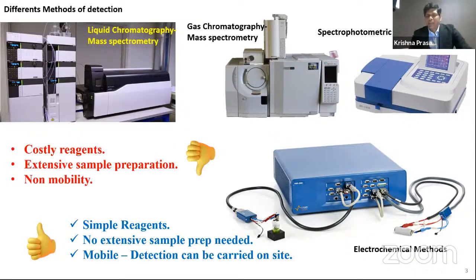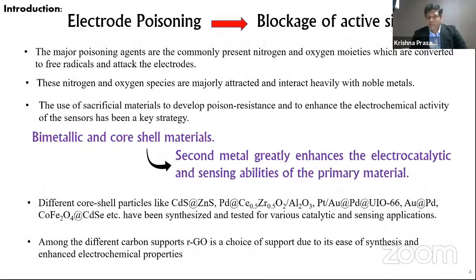However, one of the main problems for electrochemical methods is electrode poisoning, which happens because the different ions and radicals produced during the electrochemical reactions in the electrolyte lead to blockage of the active sites of the electrode materials. And the major poisoning agents are the commonly present nitrogen and oxygen moieties, which become free radicals and attack the electrodes. But we also have an advantage in the sense that these nitrogen and oxygen species are majorly attracted to and interact heavily with noble metals.